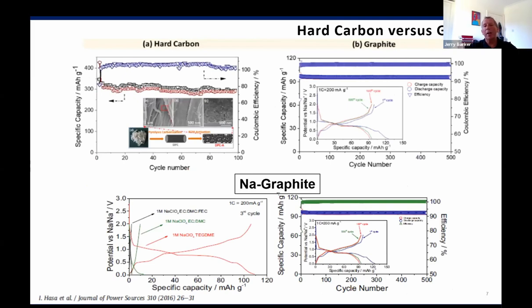Hard carbon versus graphite, right? You can think, well, why don't we use a sodium graphite system? But unfortunately, sodium doesn't intercalate into graphite to appreciable levels unless you do it with a co-insertion of part of the electrolyte solvent. And that requires you using glymes: diglyme, triglyme, or tetraglyme. And even when you do that, the specific capacity is only running at something like 100 milliamp hours per gram. So this means that we've got to use these hard carbon materials. And as I've shown on here, the hard carbon material runs at something like 300 milliamp hours per gram.